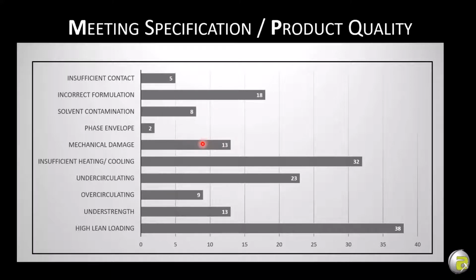And we found exactly what everybody says. If you can regenerate your solvent, keep that temperature in control, and make sure that the contact is working, then you're going to minimize the majority of your problems with meeting specification. Some of these other ones, phase envelope: if your amine is colder than the gas, you're going to condense hydrocarbons out, so that can be problematic.